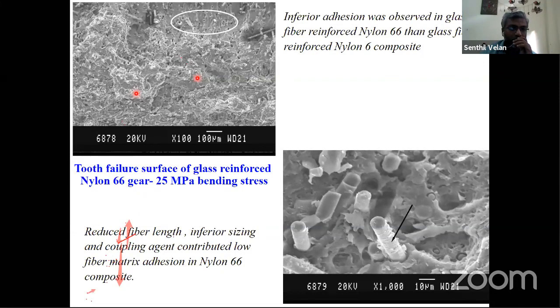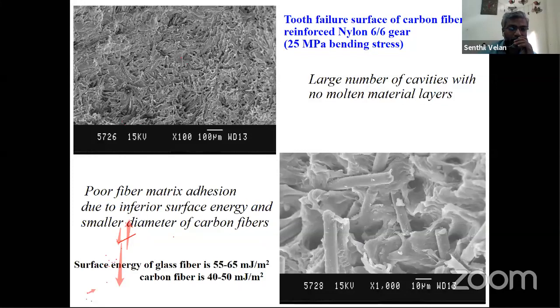And this is about carbon. You can see that huge pull out. You can see a large number of black holes and so on. You can also see pull outs over here. Typically, not only that, the surface energy of a typical glass fiber, though it was not measured, is the one which decides the wetting capability, how far you are able to join this material with another matrix. Though individually it is a better class of material, unless you take care to improve the surface energy and the issues about diameter and length, you will end up getting a poor material. In fact, that is what happened. It showed a very poor performance.